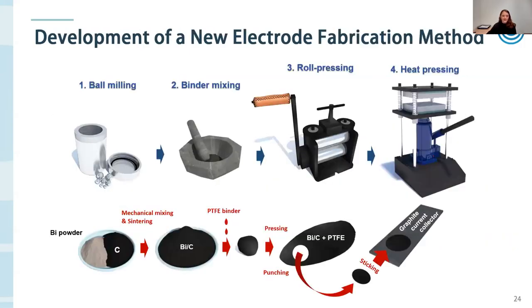And so the way that we did that was by starting with bismuth powder, which is commercially available, and using a high energy ball mill to mix that bismuth powder with carbon as a conductive additive. And then we add a polymeric binder called PTFE, and we form this little ball that has the consistency of Play-Doh. And then we put that Play-Doh through a pasta maker, and we end up with these sheet type electrodes. And after we dry those electrodes, we cut out a little circle about 1 centimeter squared and put that electrode onto a current collector. This is kind of analogous to the way that you make conventional battery electrodes.